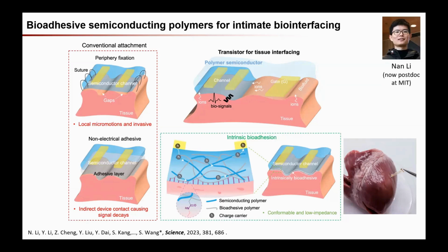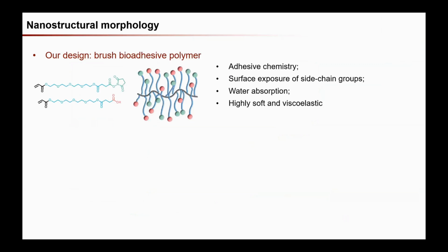But actually, long story short, after several iterations of the design, it eventually turned out that the design of the bioadhesive polymer, one of the two parts, is really the key to making this work, especially by having the right type of blending morphology, so that one property is not sacrificing the other. The main design that my student and I came up with is to have this brush kind of structure for this bioadhesive polymer. Basically, it has several design features.